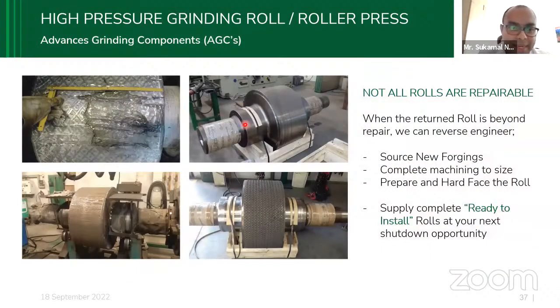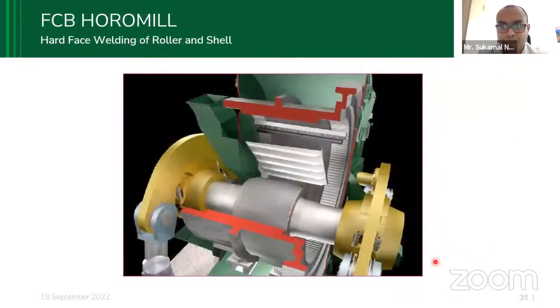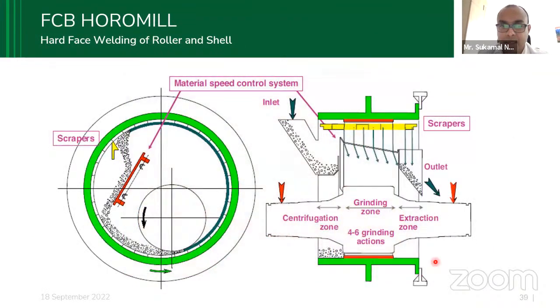This is very interesting, where it wore out during operation. So we took it out, and after using it we first ground it, removed the old layer, then started depositing, and this is how the final component looks. This is how it looks schematically. This is how the roller actually works because of this high inlet and erosion. This is the grinding zone, this is the extraction zone, and this is the centrifugal zone. These are the areas that get eroded.